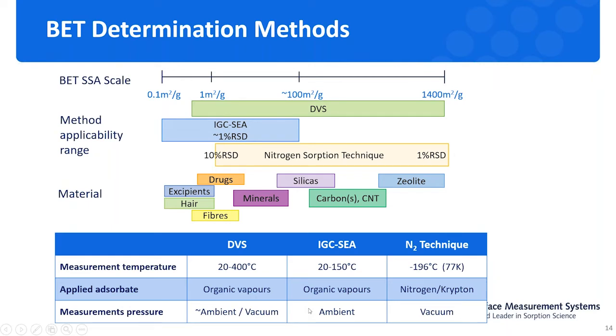perform the experiment. So with the IGC technique, we will perform the experiment at room temperature and ambient pressure, which really keeps the original nature of the material during the application or the processing, without applying any kind of harsh conditions of vacuum or liquid nitrogen temperature. And this is essentially important for some fragile or sensitive material, like some organic materials, that at some harsh condition, the sample will destructure, the structure will be destroyed, or some of the crystal will be collapsed, or the hydration water will be lost during these conditions, while the IGC technique will give the surface area of the practical sample at the real world condition during the application.